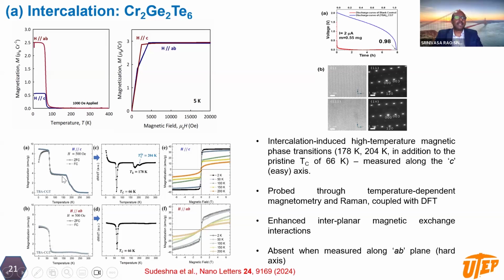But upon intercalation, you see a step-like behavior in the magnetization versus temperature graph. After taking the first derivative of it, you see, along with the pristine Curie temperature, two more additional magnetic phases, at 178 Kelvin and 204 Kelvin. These were absent in the pristine case. We also collected isothermal measurements as a function of temperature, and you see that up to about 200 Kelvin, we see non-linear behavior. That clearly shows that intercalation enhances or introduces new high temperature magnetic phases.